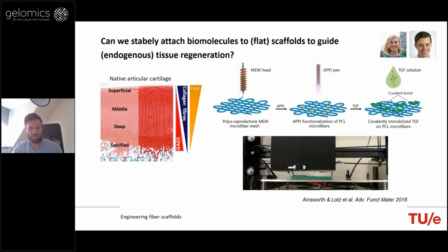We look at the cartilage just to give you an example. And in cartilage, when the collagen structure is disrupted, it's hardly being restored. In order to culture cartilage in vitro, we typically use TGF-beta because it's a growth factor known to promote chondrocytes, the cartilage cells, to differentiate and lay down their matrix, in this case collagen type 2 and the GAGs. So what we did was to take our PCL polycaprolactone mesh, and then we teamed up with colleagues in Australia from the group of physics at the Sydney University, and we investigated a technique called atmospheric plasma jets to activate the PCL fibers, and then explore if we could covalently attach or immobilize TGF-beta.